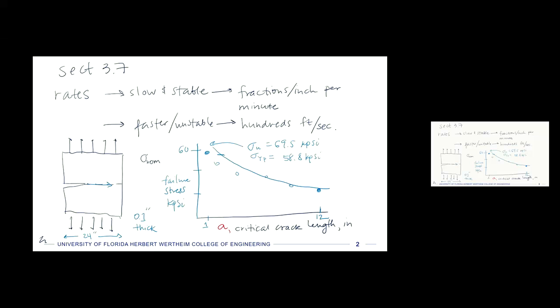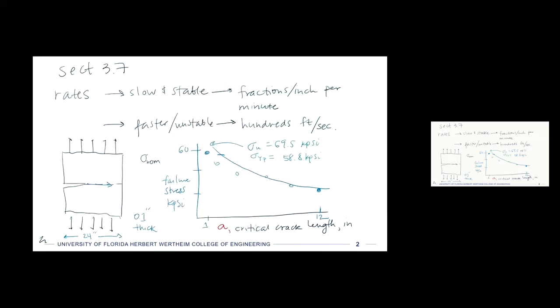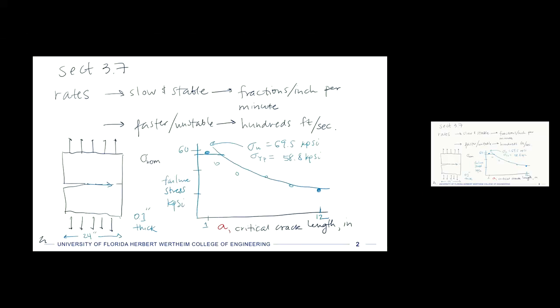So when you get to crack lengths of an inch or two or smaller, then you really have to pull on it up to above the yield point. But when you are below, you can have a crack in there such that you pull on the whole specimen with a stress lower than the yield point. And so anything above here is above the yield point, but anything below here is below the yield point, right? And so this is not the way of thinking about the stress life method with number of cycles, but rather now we're thinking about the crack length. You could consider the crack to be a flaw in the material, right?